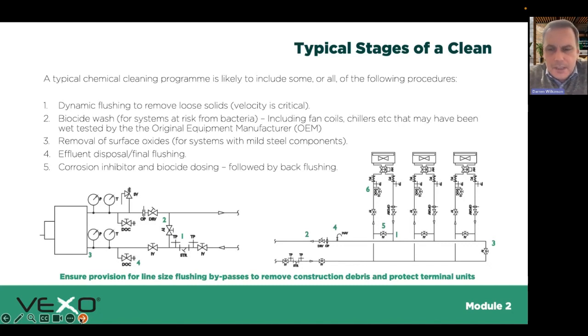They would plug on a manometer and check that they're achieving the flow rates across the horizontal branches of the pipework. So anything up to 5 millimeters in size will be moved. And you can hear this on these projects when this is happening. You can hear things tinkering, like a tapping sound almost. A little nut or a washer, in fact, I've come across. You can hear it moving its way around till it ends up in the strainer. So all that construction debris or anything that might have been put in there, any kind of sabotage even, you want to know: are you going to have a blockage, or is that system going to operate? So good flushing is really, really key. Good velocity is so key.